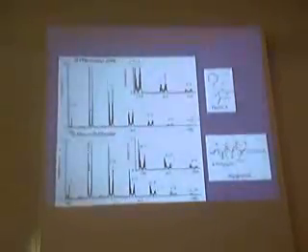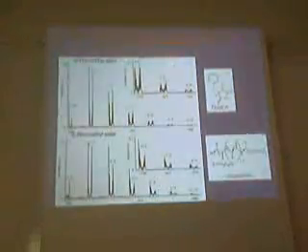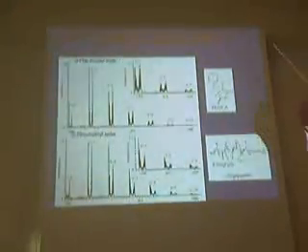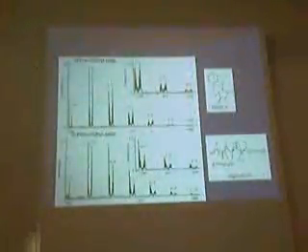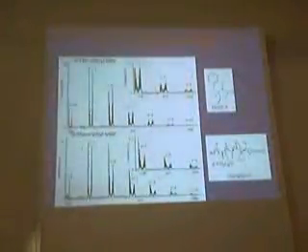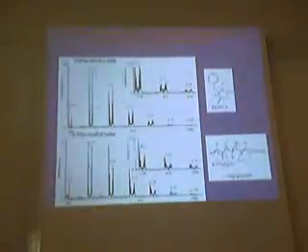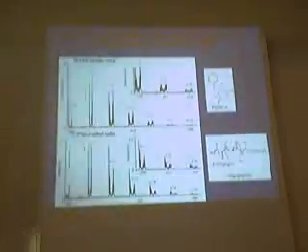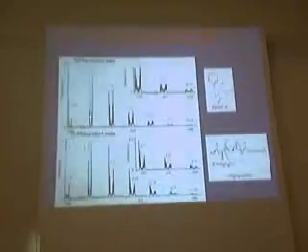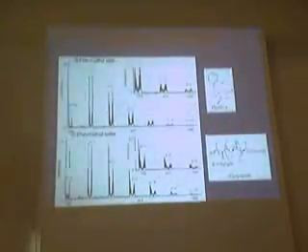The formation of the racemic beta sheet has a very important advantage, because if you want to form a helix, you have to have 8 repeat units of the same handedness. If you want to form a pleated beta sheet, you need 8 repeat units. But if you want to form a racemic beta sheet, you need only 4 to 5 repeat units. Therefore you are reducing the number of repeat units needed to form this particular helix or beta sheet, which can now enhance the formation of the chains.